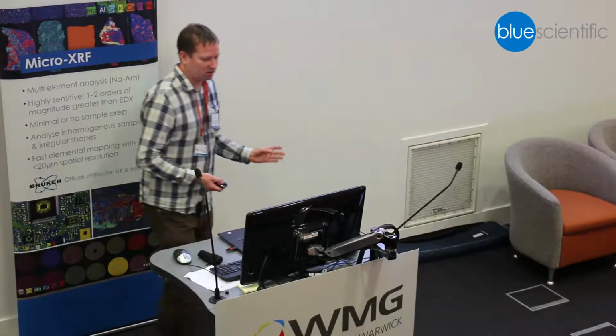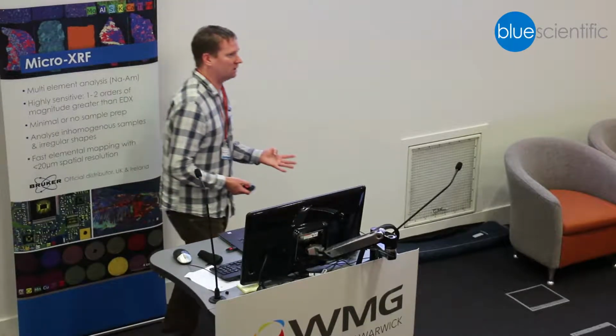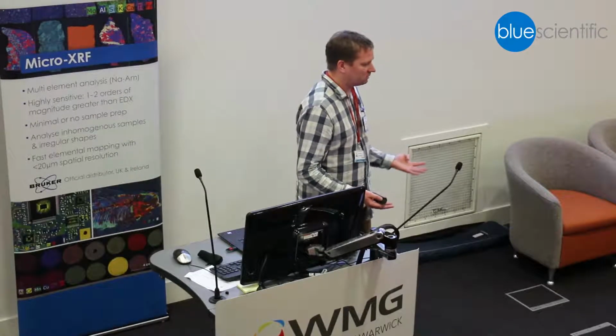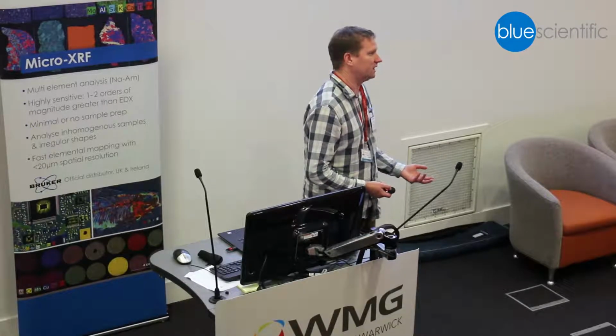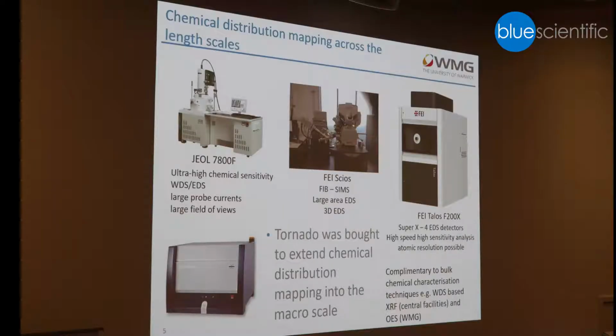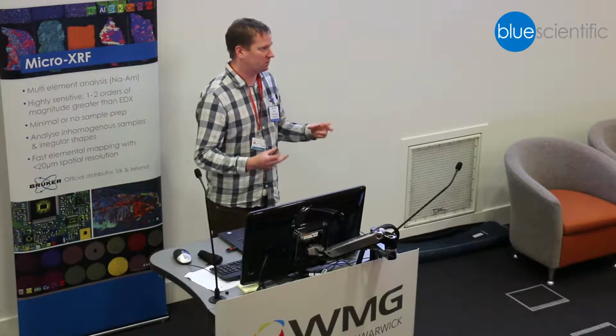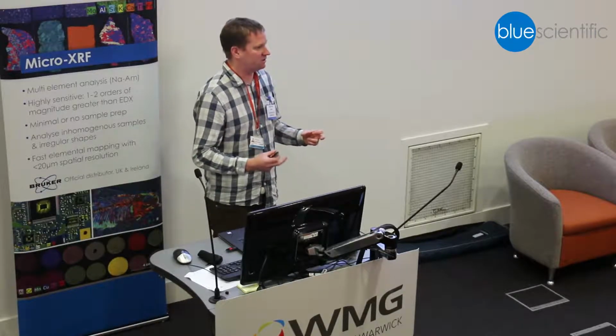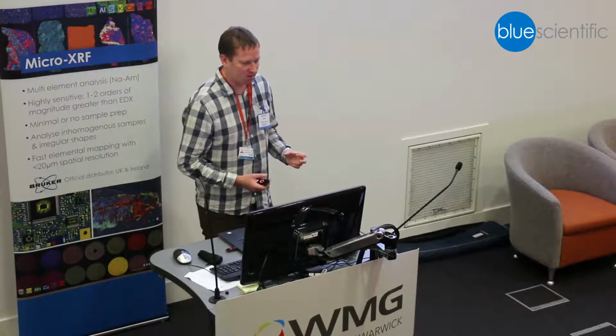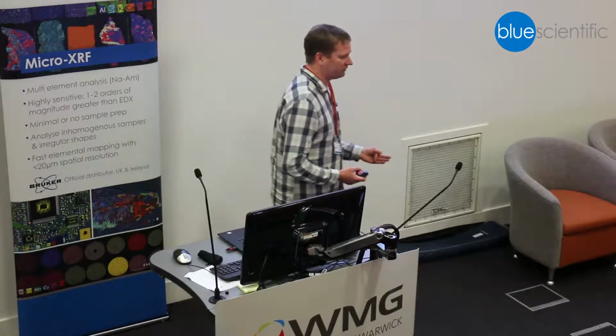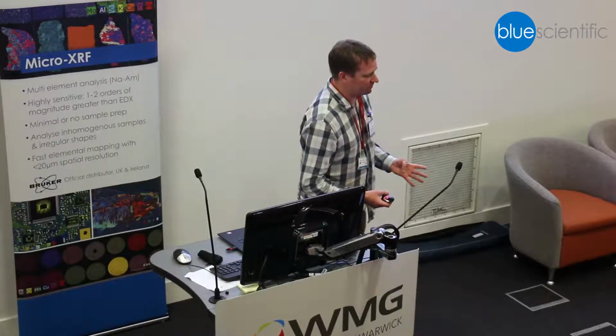Then moving down to our SEM, where we can reliably map things at the hundreds of nanometer range over maybe millimeter length scales. And then in between we've got our FIB, which has a Hiden SIMS, which can do very light element, for example, lithium detection. So we felt that we had a very strong analytical capability within our microscopes, but we thought the Micro-XRF would extend that chemical mapping into the more macro scale.